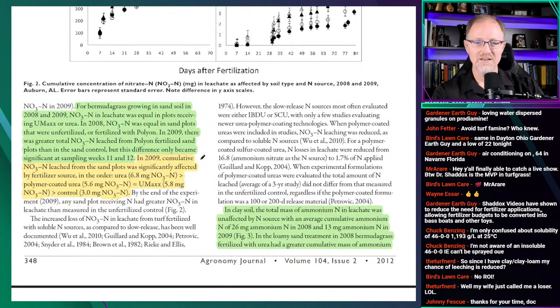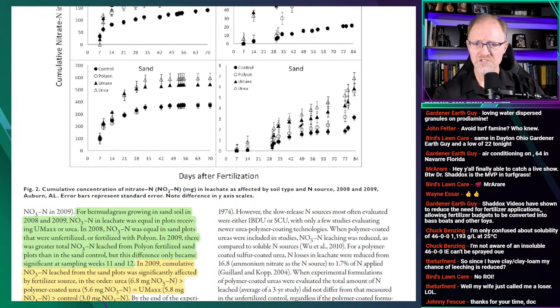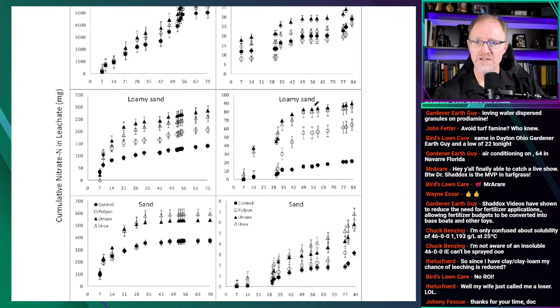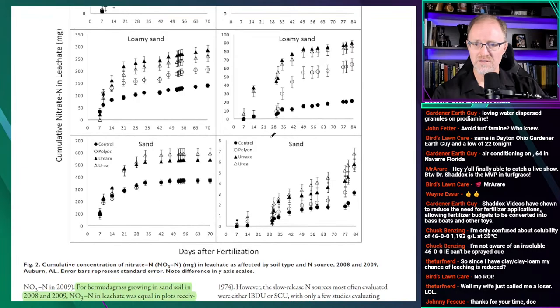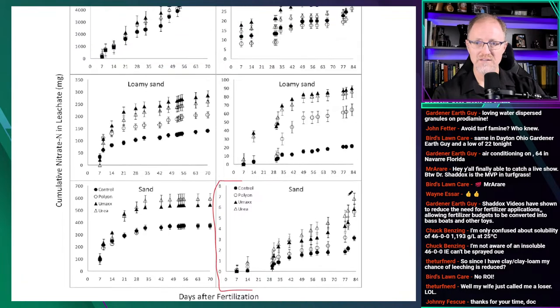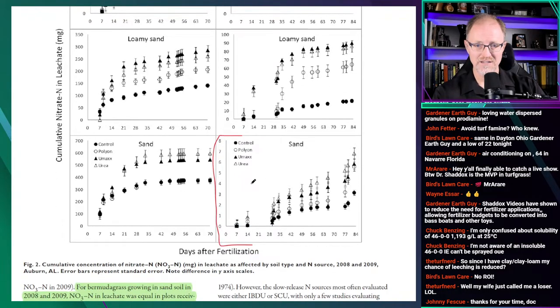In 2009, cumulative nitrate leached from sand plots was significantly affected by fertilizer source in the following order: urea was greater than polymer-coated urea, which was equal to UMaxx, which was greater than the control, in 2009, from the sand plots. What she's talking about is this chart right here, in 2009, and this panel right here, where they actually did show urea resulted in a greater cumulative nitrate leaching in 2009 in the sand, but not in the clay, not in the loamy sand, and not in 2008 in the sand.